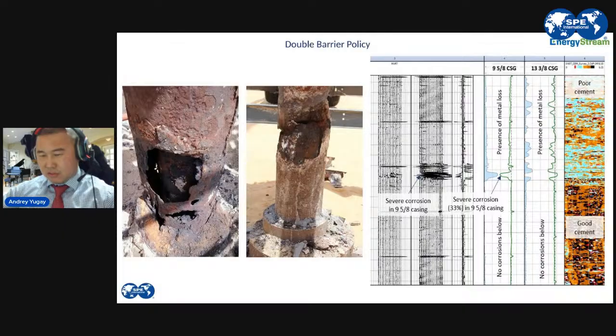Because, for example, wellhead equipment is also part of the secondary barrier envelope, but it has quite a strong, big design factor. The thickness of the wellhead is much higher than the thickness of the casing. And casing can degrade, casing can get corroded. Mostly casings are made of carbon steel, and carbon steel is not stainless steel. It's not a CRA alloy, so it can get corroded. It can get corroded externally, as you can see in the pictures on the left side. This is external casing corrosion due to high salinity and exposure to oxygen.